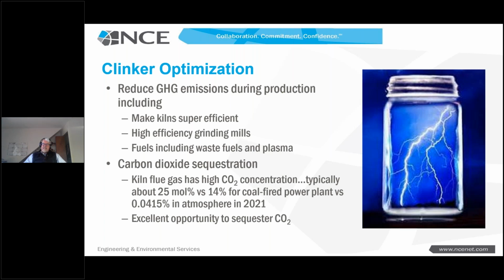The other thing to recognize is because we're basically calcining that limestone and driving that CO2 out of the flue, you have about 25% mole volume of CO2 in the exhaust gas of a cement kiln. That is a great place to grab CO2. It's a great place to sequester CO2.